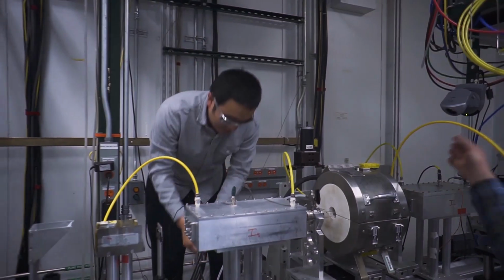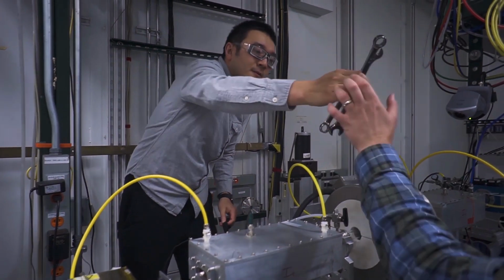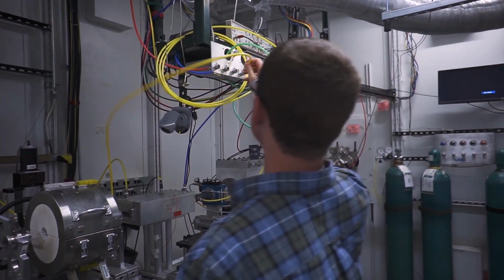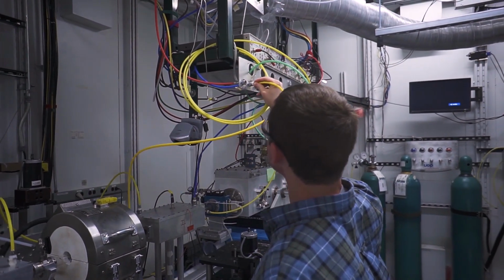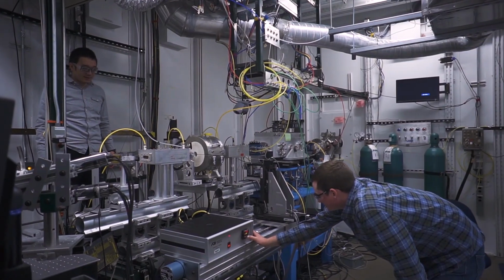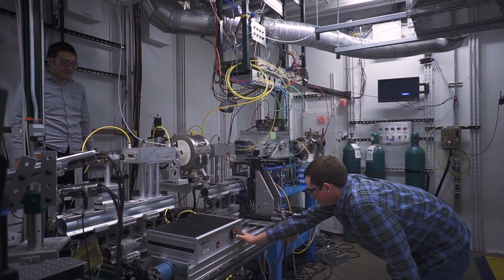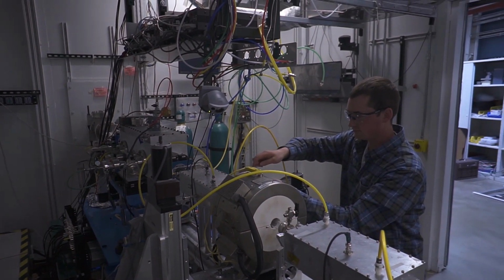We also not only look at those properties that control catalyst activity and selectivity, but we look at the changes in the catalyst properties as the catalyst deactivates. We then use this information to understand what is driving catalyst deactivation. We then can pass this information along to NREL, which helps them to develop synthesis techniques that then not only optimize the catalyst performance, but also increase catalyst lifetime and durability.